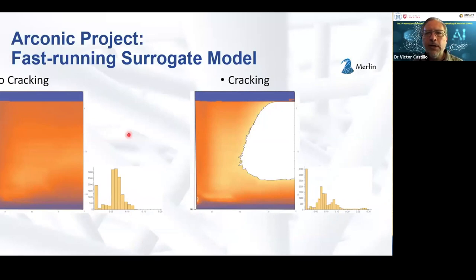And so what I'm showing here on the left is a case where there's no cracking, there's no residual stress, and we have a distribution of the hot tearing indicator, which is a measure of residual stress. And the distribution shows a very low average for the hot tearing indicator. On the right-hand side, we have a case where there's a lot of residual stress and cracking is likely, and you can see the distribution is much higher for the residual stress.